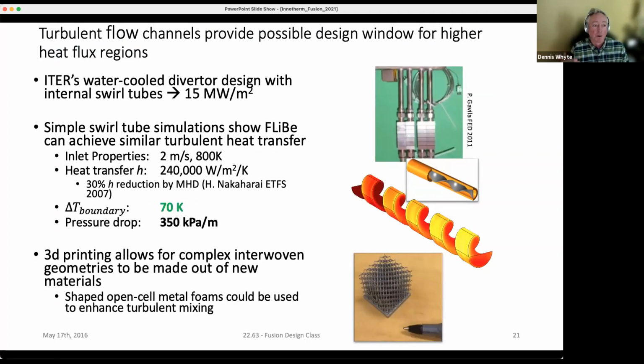But the actual details, particularly when it gets into the high heat flux components, are much more difficult. In those regions that I talked about where the concentrated power is, we have to deal with power fluxes well in excess of a megawatt per square meter of surface heat flux. Again, I can't get into too much of the details, but this shows the beginnings of thinking about innovations. In our case, our working fluid is a molten salt, and we were trying to figure out if we could use a pretty established technique like swirl tube technology to enhance the heat transfer with reasonable pumping power and pressure drops in this environment.